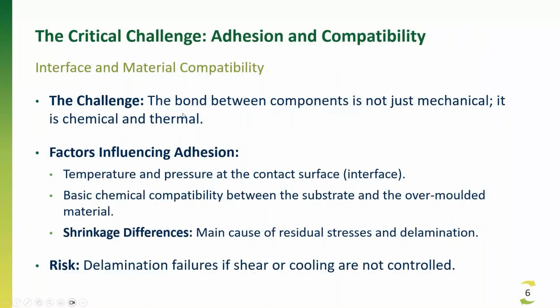In our case, the challenge is to bond between the different components in a way that might not be mechanical, but we want it to be a chemical bond. There are several factors influencing this: temperature and pressure, of course, during the injection, because you have to understand that the material that is going to be injected is melted, so at really high temperatures, and at high pressures in order to fill the whole cavity in just 1 second, because that's the time that we usually use. We are talking about 200 bars suffered by the material. So the amount of pressure that can be transferred into the materials that we are over injecting is quite big.